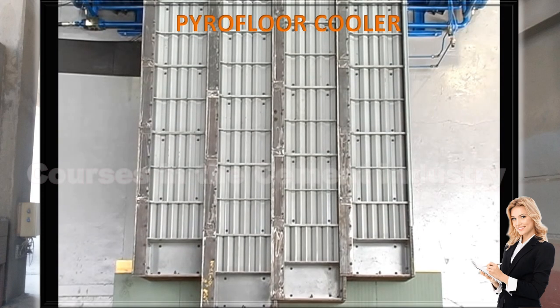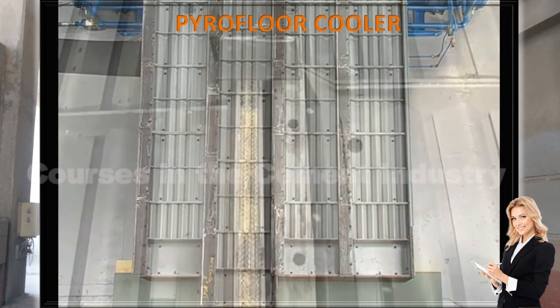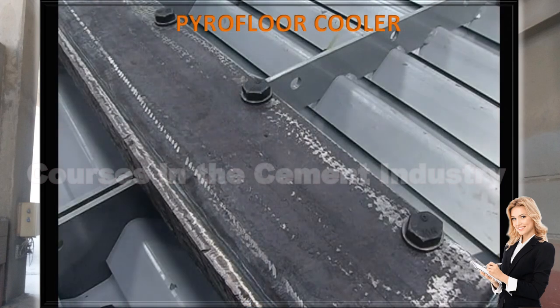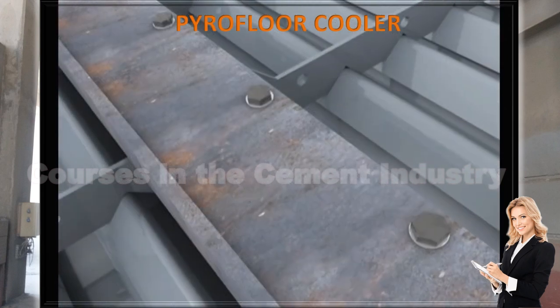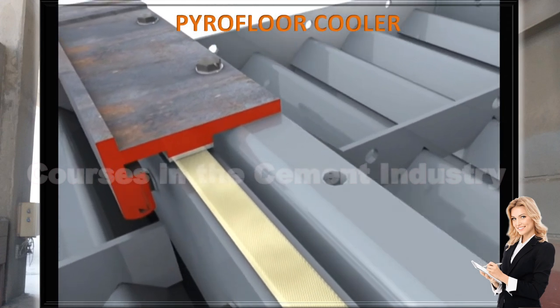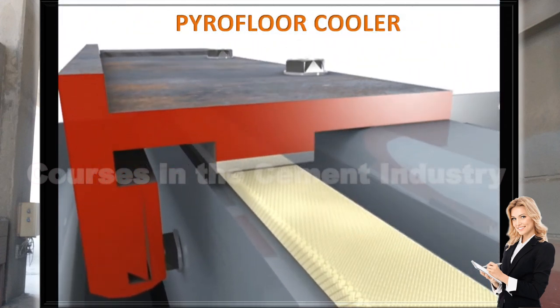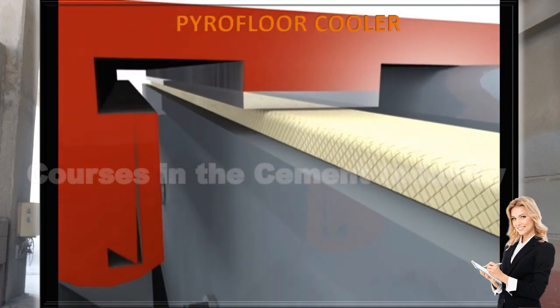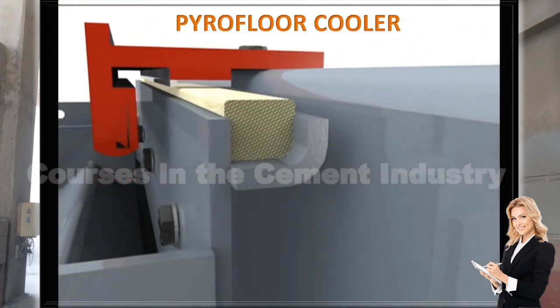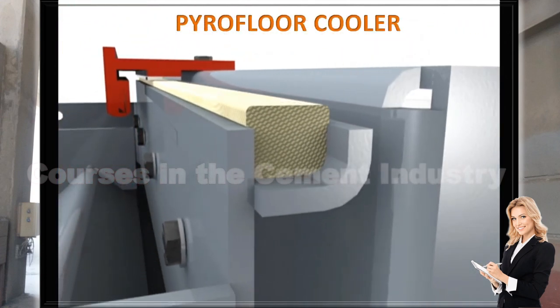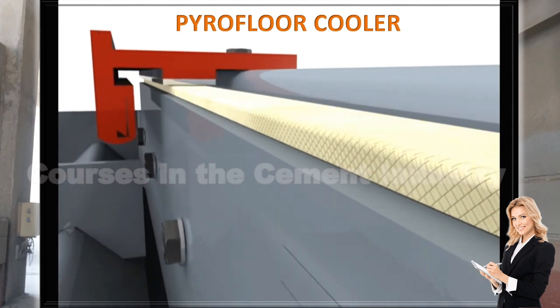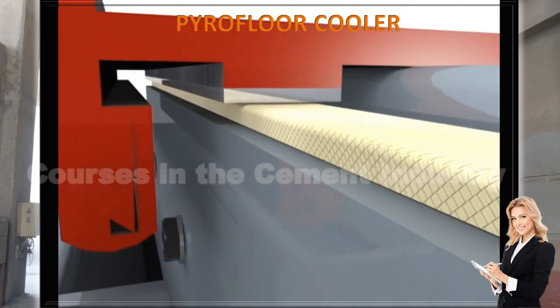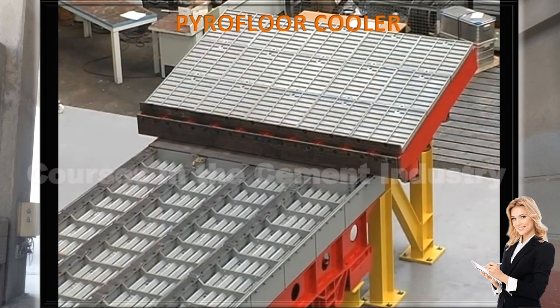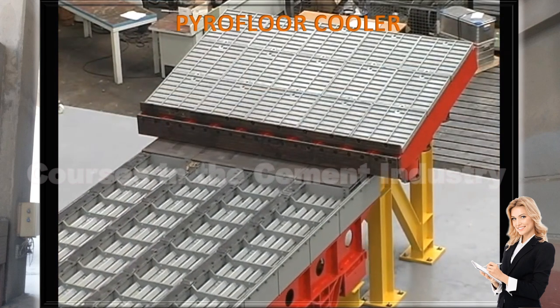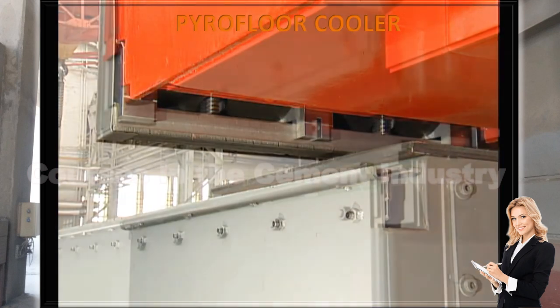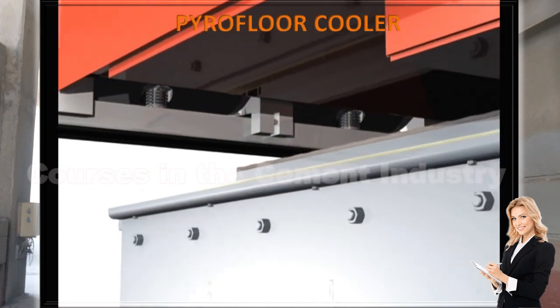The Pyrofloor clinker cooler utilizes newly designed unique contact seals for all those places where air could otherwise stray through labyrinth gaps. By this technology, neither air nor clinker can find its way through gaps where it should not pass. Due to the contact seals and due to the fact that there are no elements passing through the grate surface, there is no possibility for clinker fines to fall down below the aeration surface. Hence, any spillage provisions like hoppers and drainage are no longer necessary.